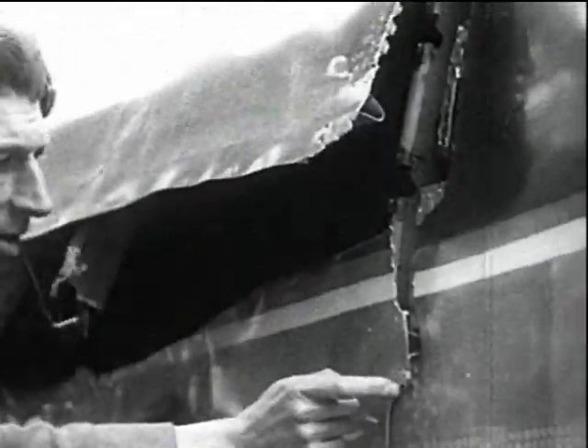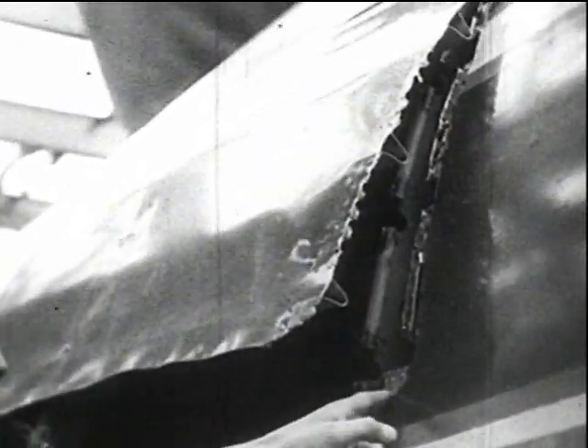A small fatigue crack in the skin of the rivet near an escape hatch is considered to be the start of the failure, which developed rapidly. The damage was then repaired, and also a crack believed to be the beginning of another major failure. The tests then continued.